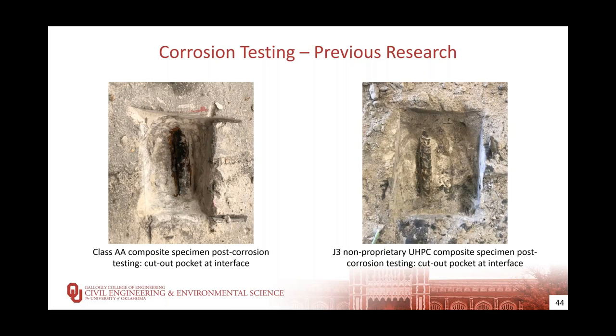From these, you can see the J3 connection on the right fared a lot better than the class AA mix. It is also important to note that no halo corrosion was present in the J3 mix, which is a common issue when exposing rebar for repair.